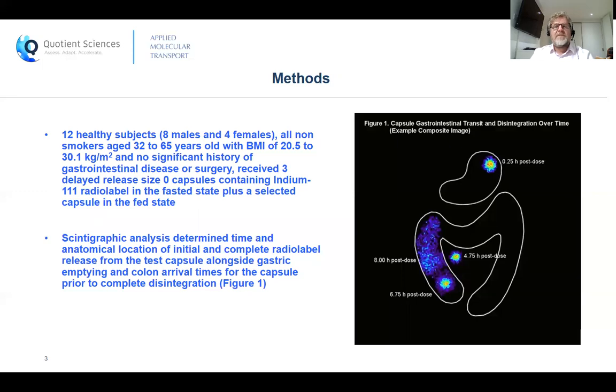The study enrolled 8 male and 4 female healthy volunteers who met the inclusion criteria, as were all non-smokers with body mass index between 20.5 to 30.1 kilograms per meter squared and no history of GI disease or surgery. These subjects received 3 delayed release coated size 0 capsules containing the radio label in a fasted state. Following a within-study interim review of emerging data, the subjects subsequently received one of the 3 coated capsules again in the fed state. Figure 1 on the right of this slide is a composite of the gamma camera data generated